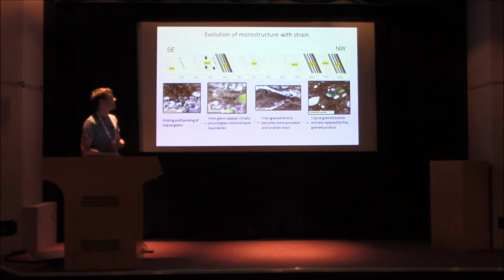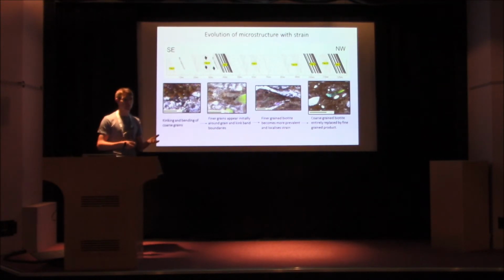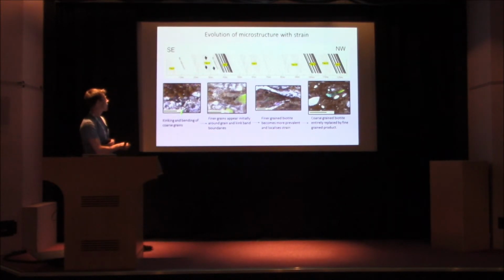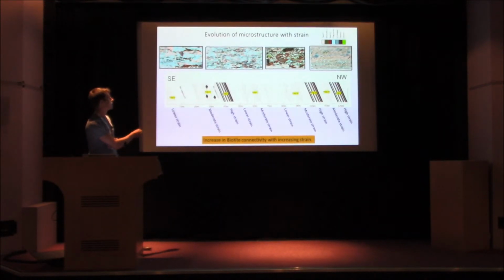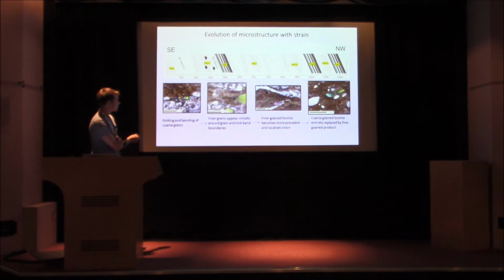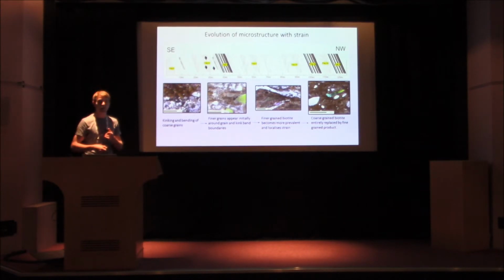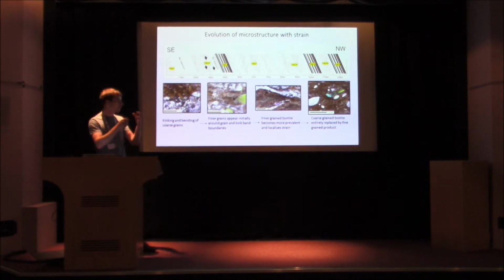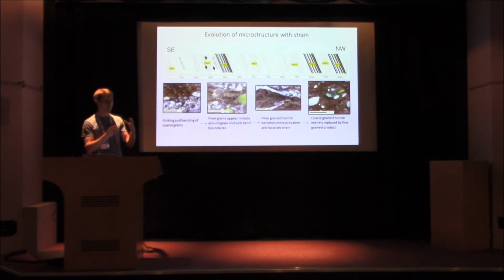So what's the microstructure of that biotite? How is the mica deforming? Well, these are the same stages of strain as I showed you on the previous slide. Initially, the biotite is the dark phase in these micrographs. Initially, you have kinking and bending of the mica grains. So you've got quite coarse, quite large grains, and they bend and kink and deform that way.